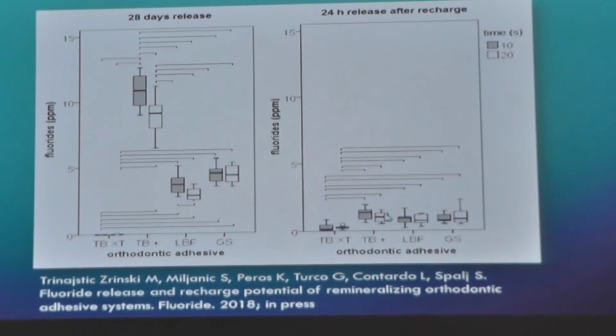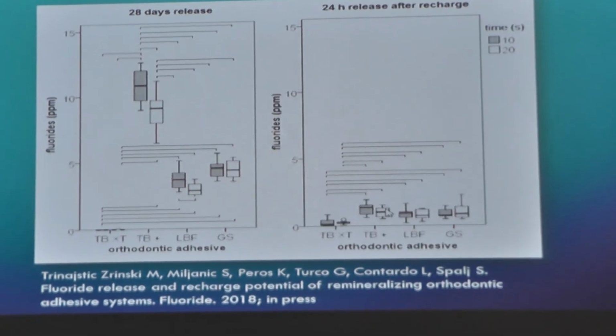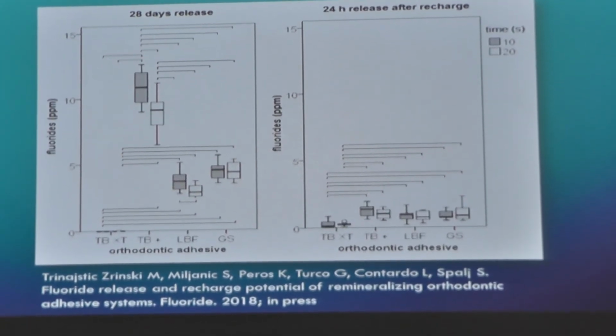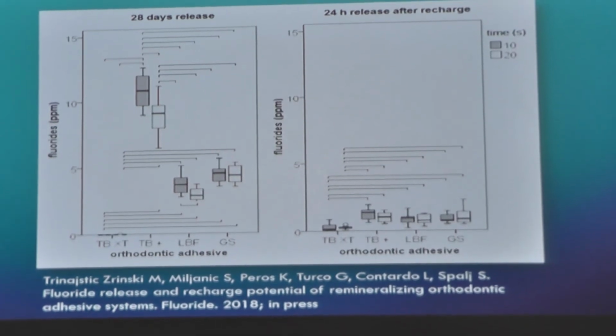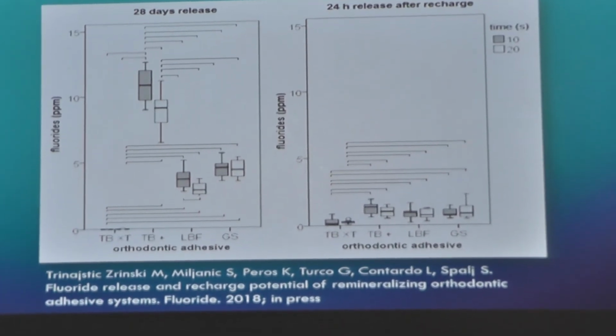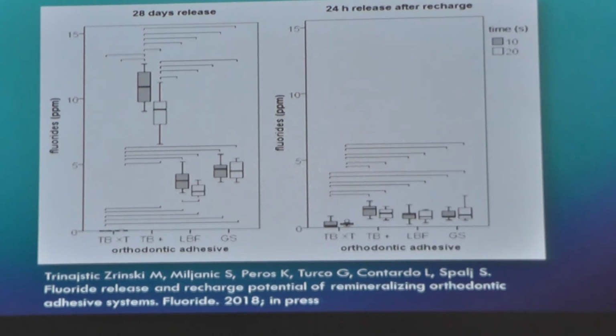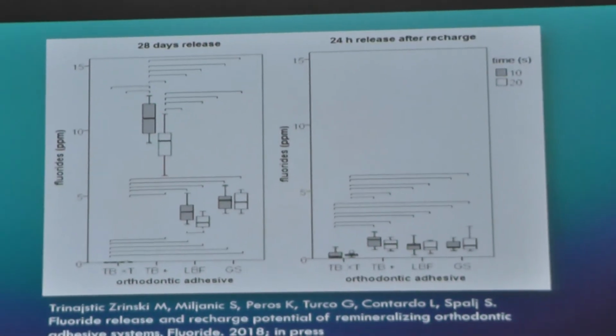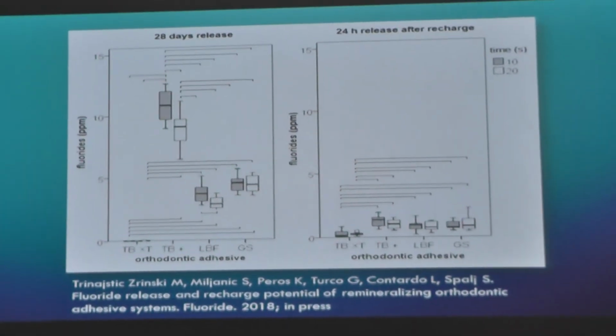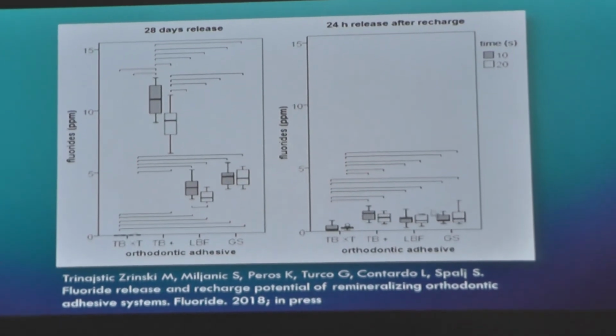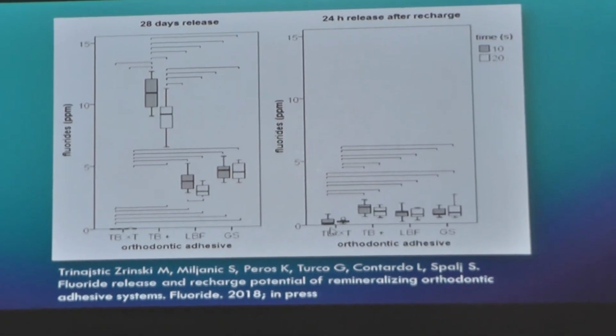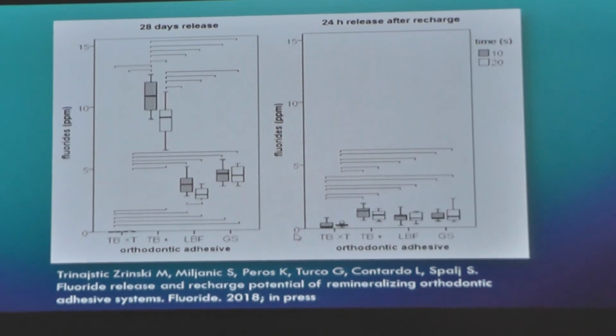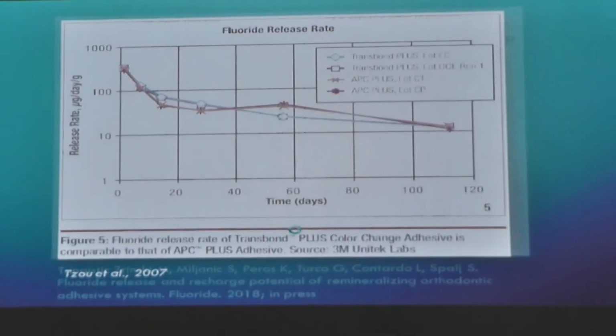And also, we thought maybe if they do not release for a long time, we could recharge them. So if the patient put remineralization gels or something on the brackets, the adhesives would incorporate this fluoride and then release it afterwards. But this potential is very, very low, as you can see. So they cannot really be recommended for this purpose.